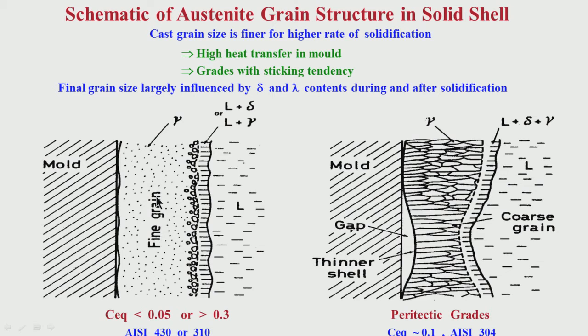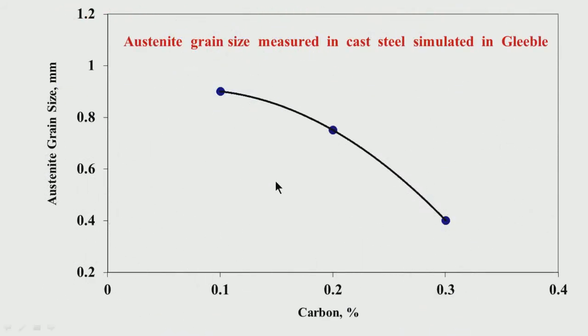Sticking means there is no air gap formation between the mold and the, what is that called, solid shell. Here you see the gap formation is quite large, here the gap formation is minimum, quite low. So the possibility of grain coarsening is quite less here for sticker grades, but for peritectic grades you have the possibility of grain coarsening. So you can actually see what the austenite grain size is when you simulate under Gleeble.